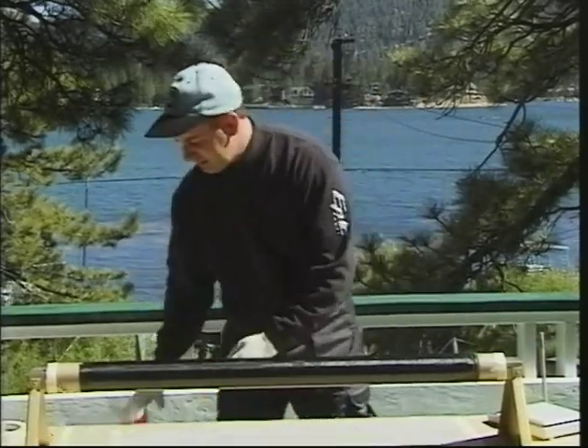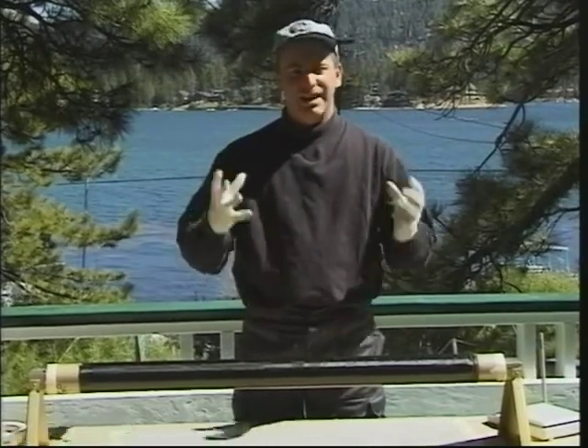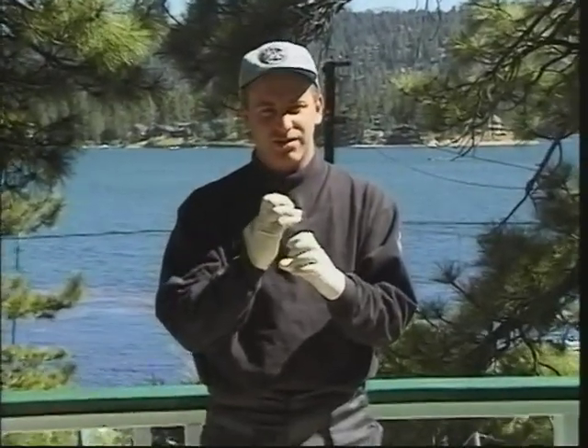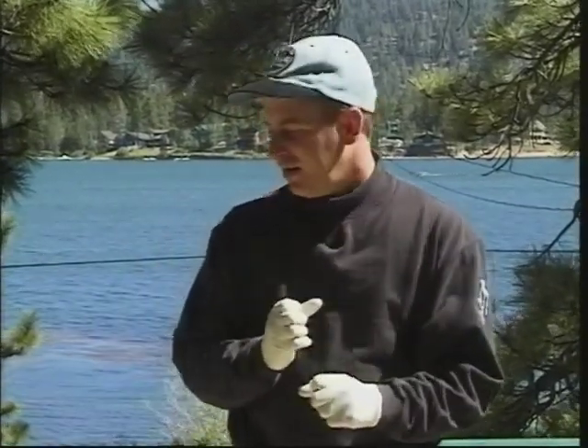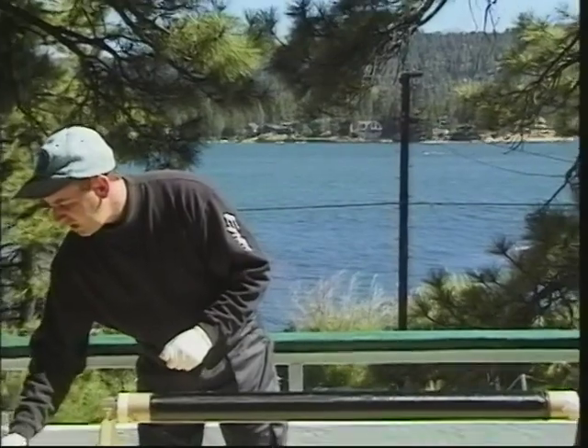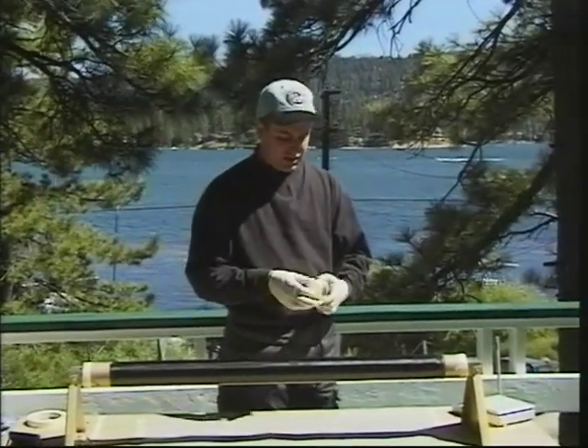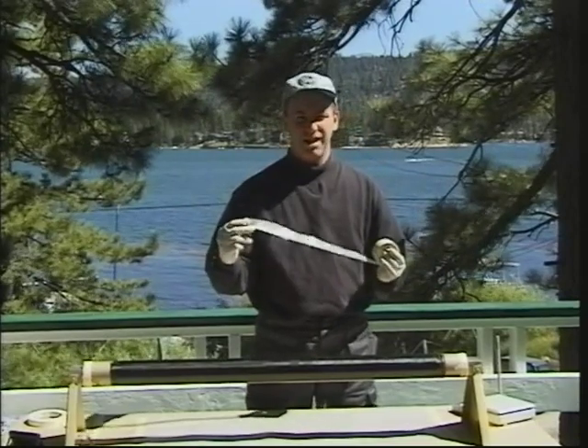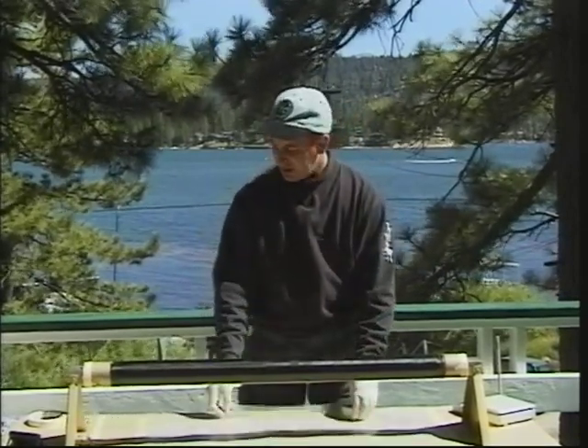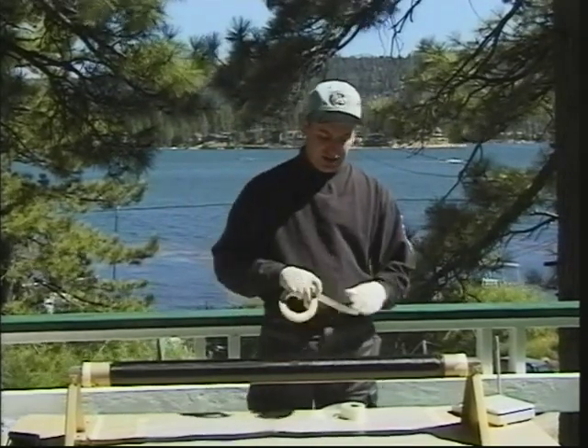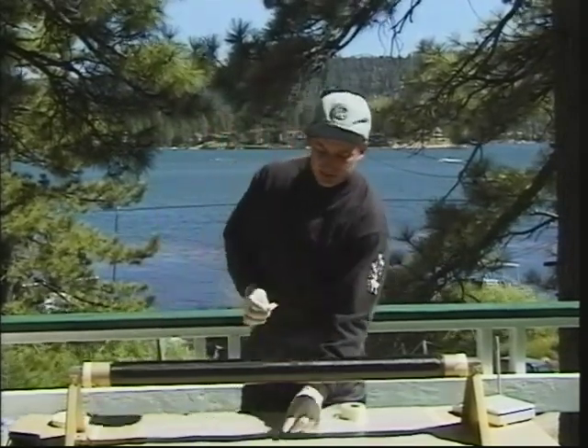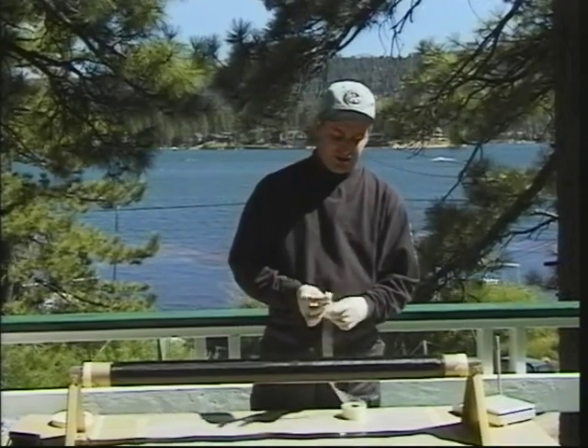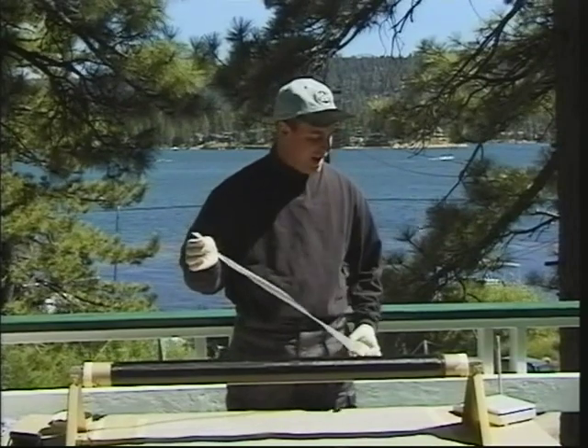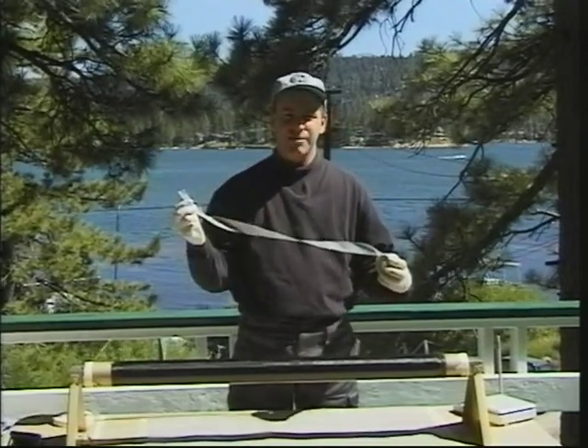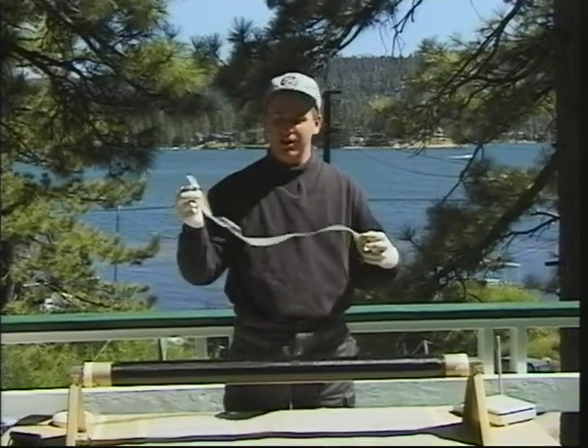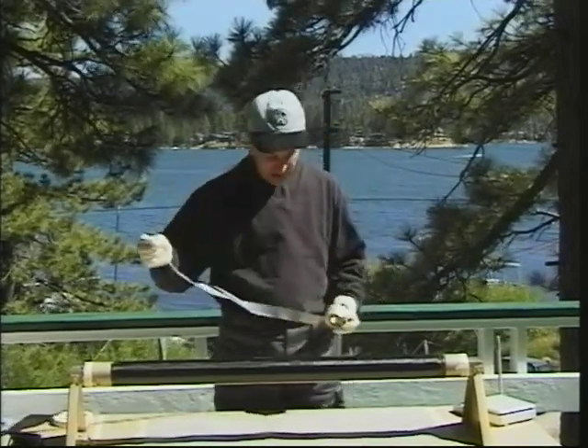the key with this heat tape winding or with the vacuum bagging is to get those layers compacted together good and strong and bleed off the excess resin. And that's what creates a good structure. To that end, we sell a product, and it's a specially formulated heat tape. This tape does exactly what it sounds like it does. During the cure cycle of the resin, this tape heats up and squeezes on the laminate, compacting those layers and bleeding off the excess resin where the tape layers overlap. Now the way to use this tape